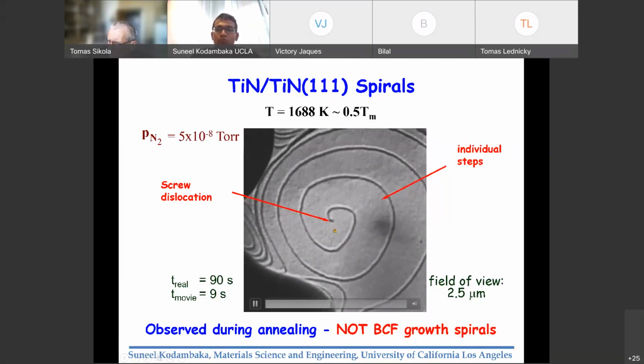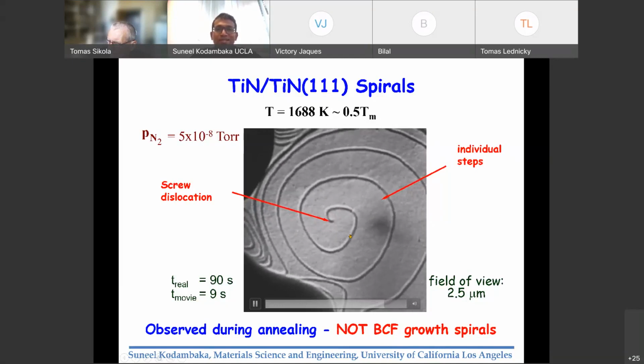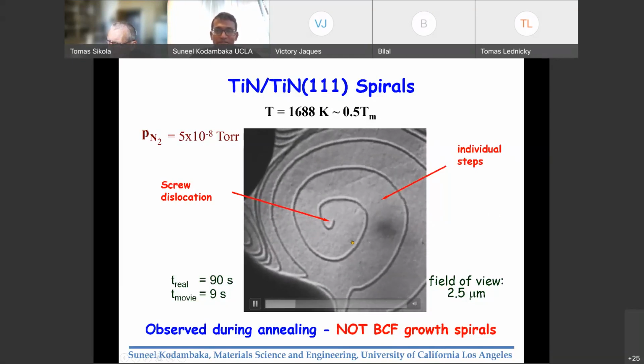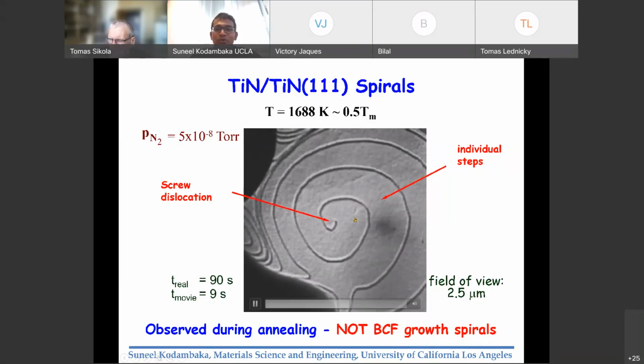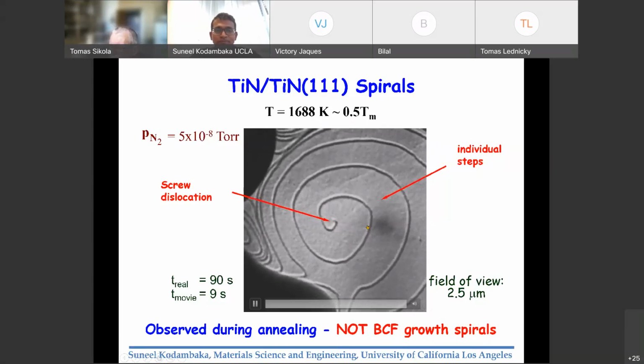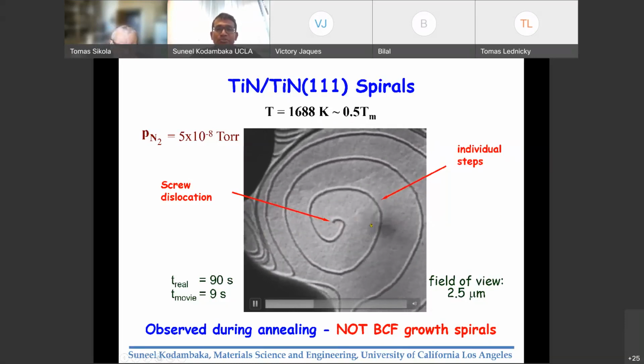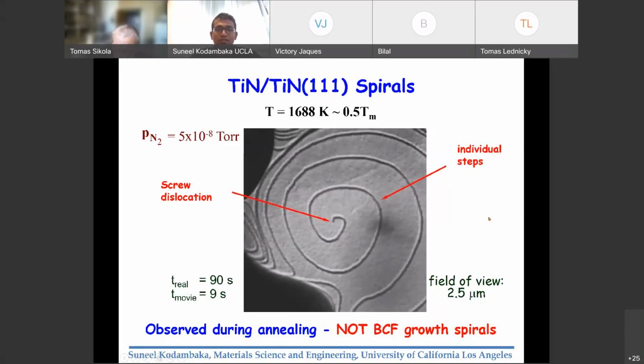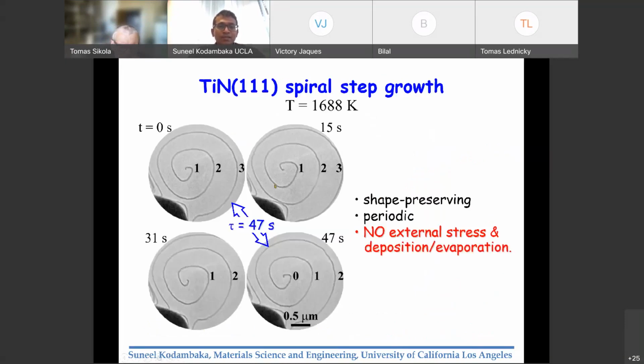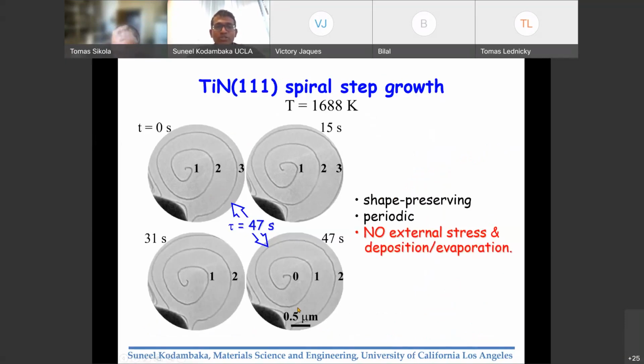But here I want to point out that what we are observing is not a growth spiral, because we are not depositing material. We are not desorbing material from the surface. This temperature is not high enough for titanium or titanium nitride to desorb. So essentially what we are observing is surface transport and maybe bulk transport, and I'll tell you that in a second. From these measurements of this spiral step motion, we can measure the angular velocity and the time it takes for the spiral to appear exactly the same, which is about 47 seconds. So it repeats itself, and there is no external stress, no deposition, no evaporation.